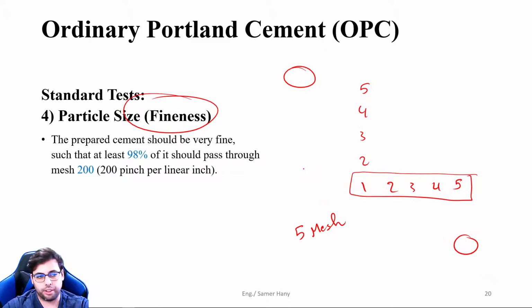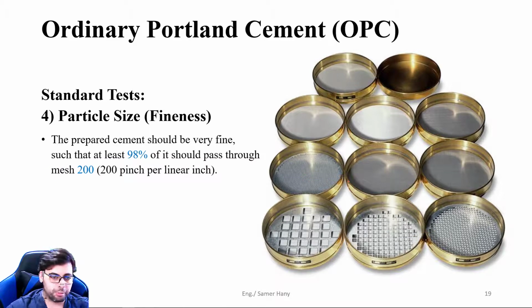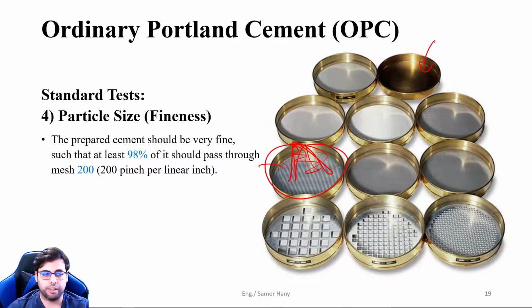Okay, so going back to the screens, let's remove all of the notes. If we select, let's say this is the 200 mesh screen, and we get like 100 grams of cement above that screen and screen them well, we need to get 98% or above going through that screen, maybe into the pan here. This will be under the screen while we're screening, and only 2% or less should remain above that screen. If it's higher, maybe 5% above and 95% below, this means that our cement is not conformant to the standards, and we need to grind it a little more to make it finer. Okay, and this means, of course, expending more energy, but we need to meet the standards here.